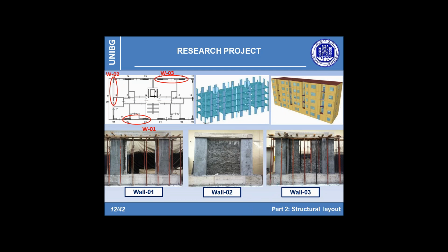In particular, 3 different specimens were extracted from the external envelope of the building as reported in the slide. This is to study the hysteretic response of the designed structure and to investigate the interaction between infill and structural shear walls. The specimens have the same dimension and differ only in respect to the presence of a light infill panel that can also present an internal window opening as depicted in the slide.